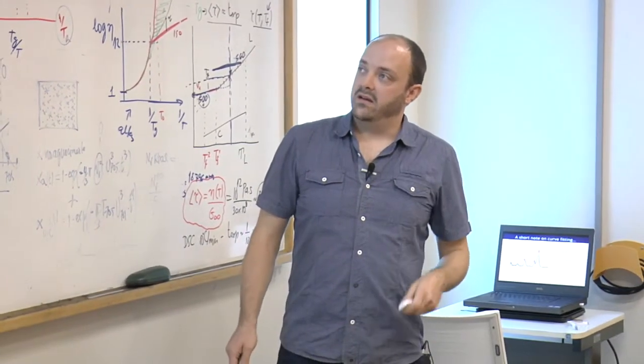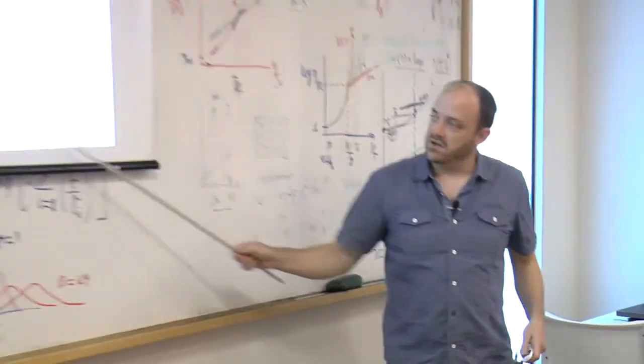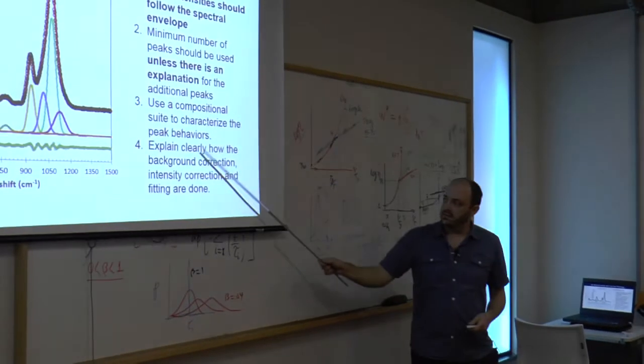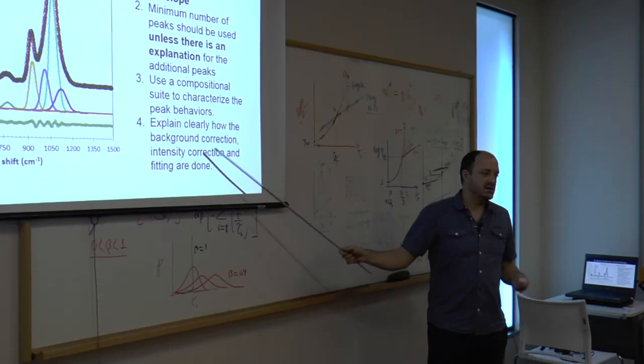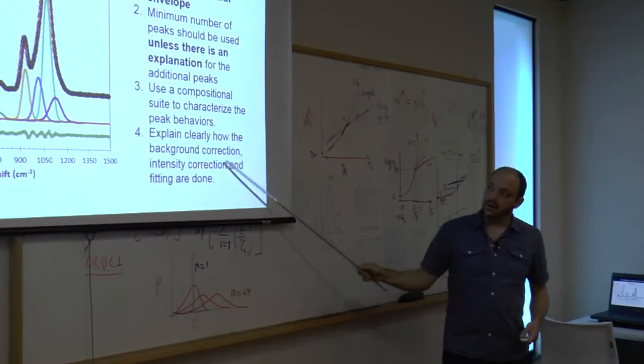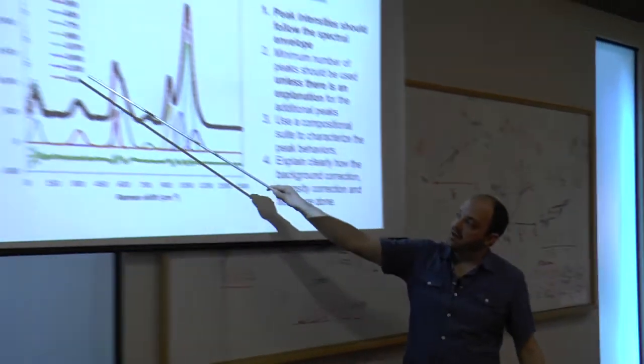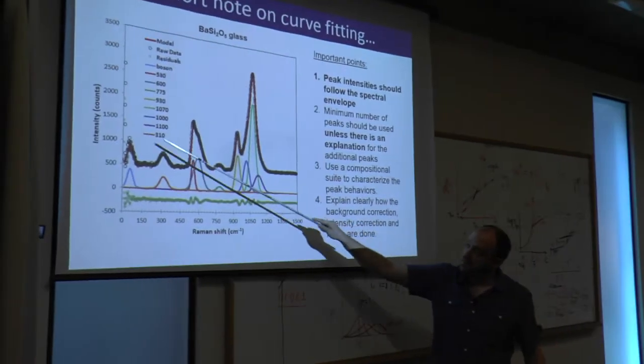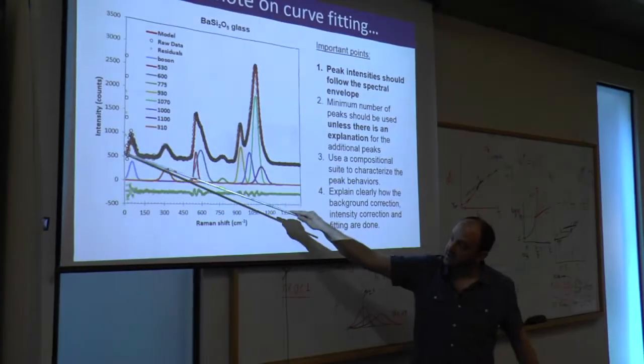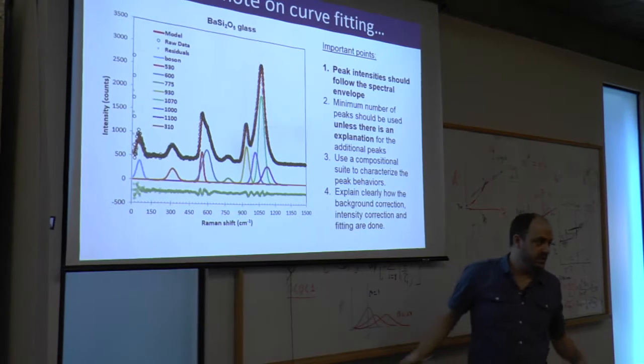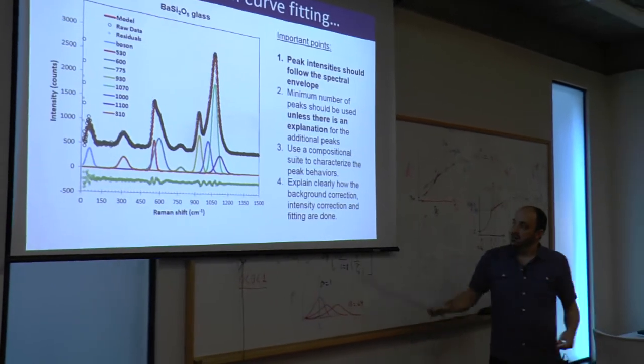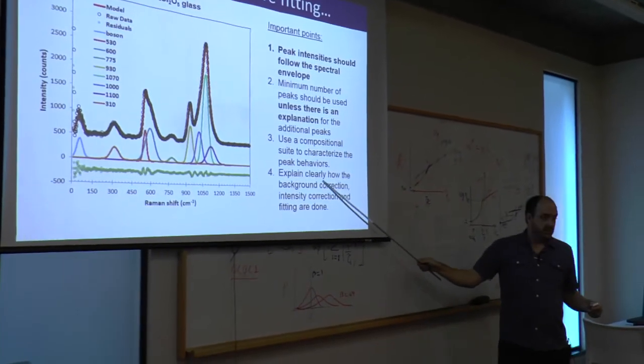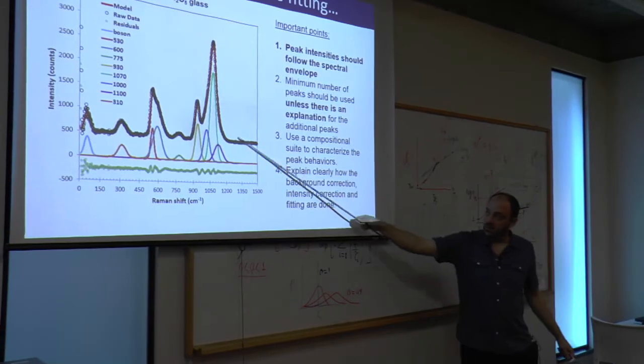The last thing, and something that's overlooked, especially by people who publish a lot of papers, is that they don't always explain how they make their background. We saw that there's a huge slope at low frequencies below here related to the boson peak. This is actually the boson peak after you take off a background. Whatever you do, explain clearly how you've removed the background to get to the point where you can make this